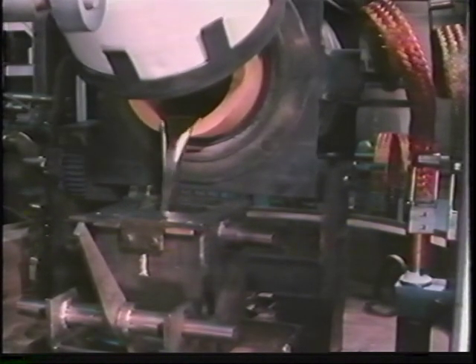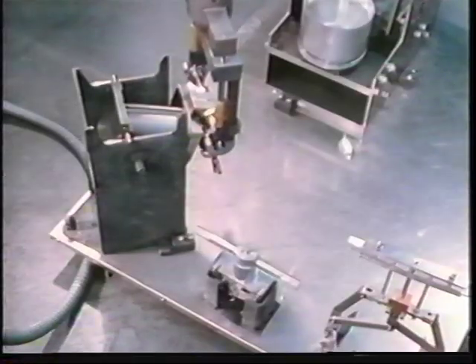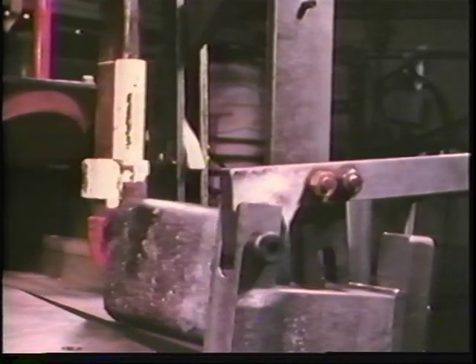In this fuel purification step, a molten salt is used as the electrolyte. The crucible is the anode, and a rod immersed in the molten salt is the cathode. Deposits of uranium or uranium-plutonium from the core or blanket feed collect on the cathode. The residue remaining is a waste stream. The purified product of electro-refining is cast into ingots of metal, and the composition of the core fuel ingot is tested and adjusted to the desired level using plutonium and uranium obtained from the blanket.